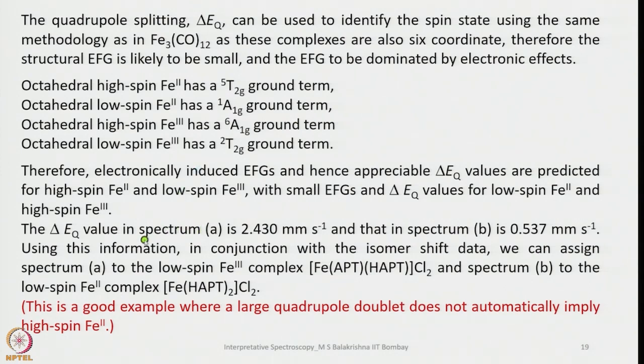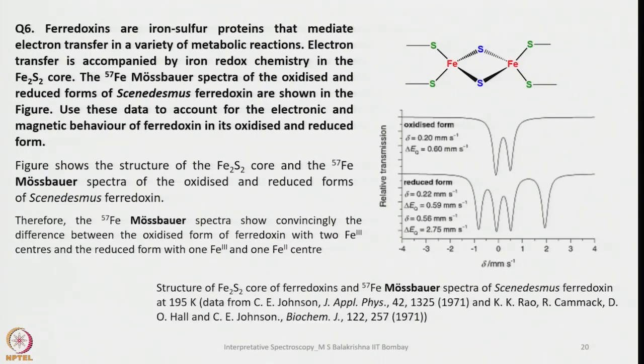So this value in spectrum A is 2.430 millimeters per second, and in spectrum B it is 0.537 millimeters per second. Using this information in conjunction with the isomer shift data, we can assign spectrum A to the low spin Fe3+ complex, that means this anionic ligand here, and spectrum B to the low spin Fe2+ complex where HAPT is a neutral tridentate ligand. So this is a very good example where a large quadrupole doublet does not automatically imply a high spin iron 2 state. Now let's look into one more example.